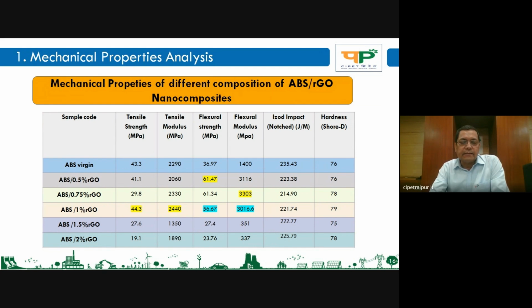Like in tensile testing, tensile strength in MPa has gone from 43.3 for virgin ABS to 44.3. Similarly, tensile modulus is 2290 to 2440. Flexural strength is also 86.67. And in flexural modulus there is a phenomenal increase, almost double, 1400 to 3000, more than double. In Izod impact there is slight variation. And hardness has also increased in the 1% combination of RGO, which has come to 79 against 76 in case of ABS virgin.